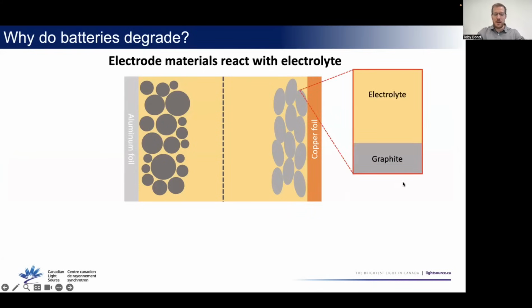If you zoom in at the negative electrode, so these are particles of graphite over here, once the surface comes into contact with electrolyte, it forms a surface film. In technical jargon, we call it solid electrolyte interphase, or SEI, but I'll just call it surface film because that's easier to remember. Initially, you form a thick surface film, and over time it keeps growing a little thicker and thicker. But as time passes, the subsequent layers get thinner and thinner, because this layer actually protects the graphite from further reaction. So it's very reactive initially, but if it forms a nice stable film, that prevents it from reacting quickly, and it slows down the rate of reaction over time.